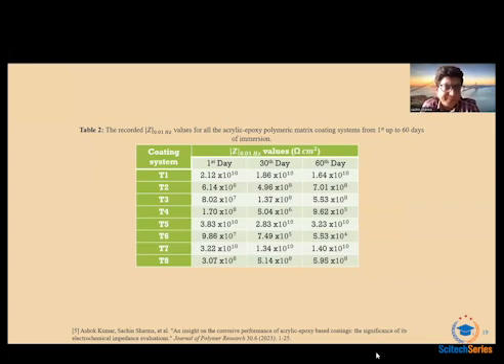However, for the remaining samples, for example, T2, T4, T6, and T8, we could see that some of the samples had an order of magnitude reduced by 1, which indicated poor corrosion protection performance against the penetration of the electrolyte ions. So it would reach the metal substrate interface at a faster rate.